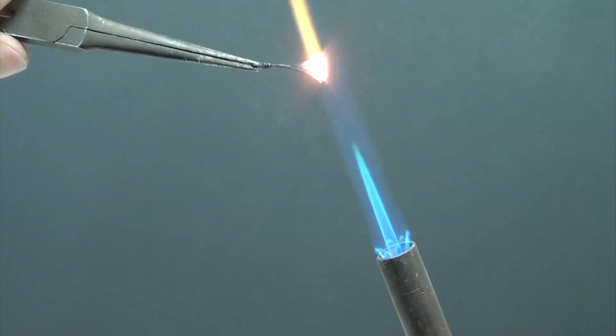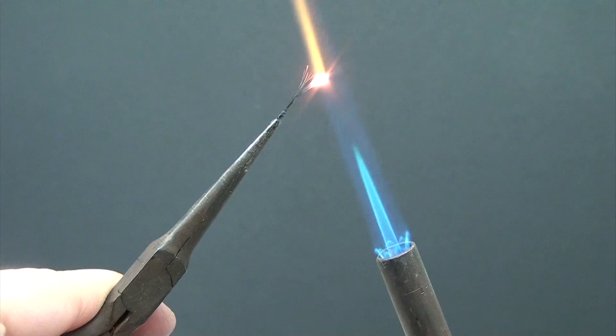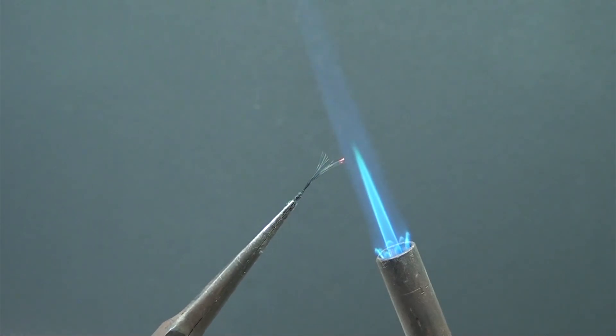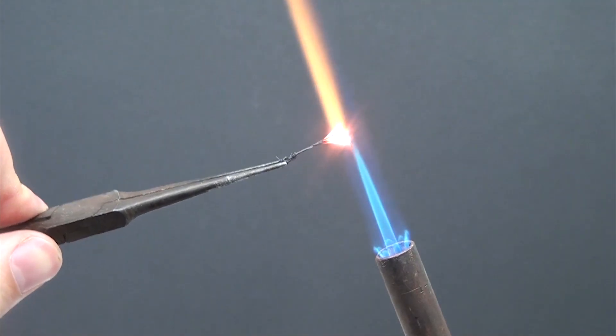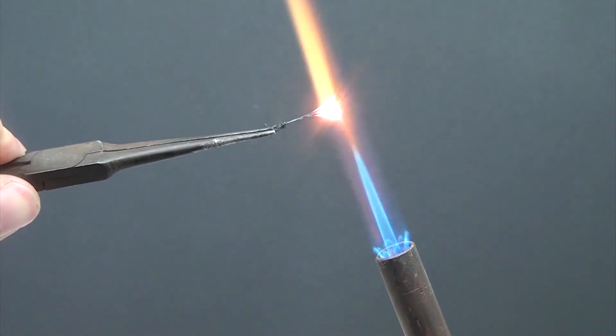and eventually realized that just holding the bunch of wires in a blowtorch flame sharpens them nicely. Tungsten is neat in that its melting point is so high that it'll oxidize and turn into powder long before it melts in air, and it does that at the hottest parts first. So if you do it right, you end up with these incredibly sharp tungsten needles. One trick though is to not bunch the tungsten up too much while doing this so the heat can spread evenly.